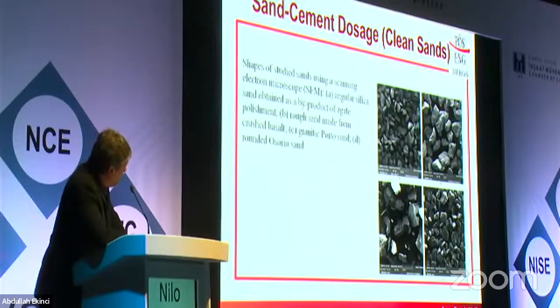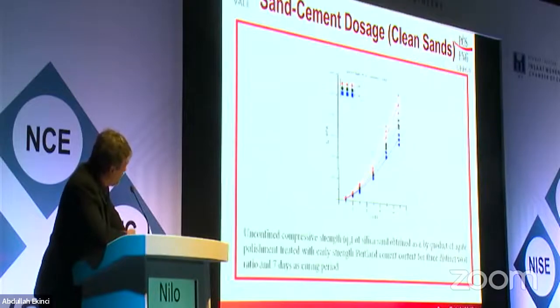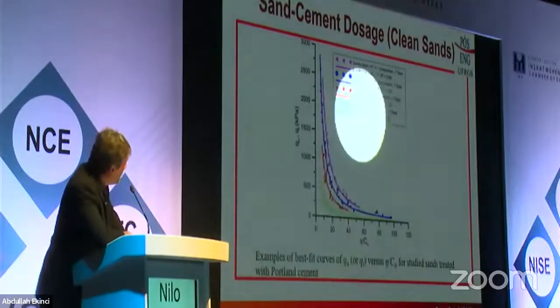Okay, but we have carried out basic tests such as unconfined compressive strength and splitting tensile for these materials, and for each one of them we have used different cements, different amounts of cement, different densities, and so on. We can see here some results: this green one is the result for several amounts of cement and several densities, just for the splitting tensile strength, and we can get this unique green curve. And the other curves, the red one, the blue, magenta, and so on, are the other materials from those four materials with different amounts of cement. As I said, the green one is splitting tensile, the others are unconfined compressive.